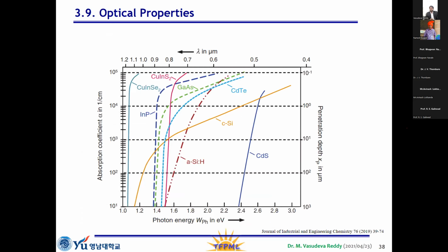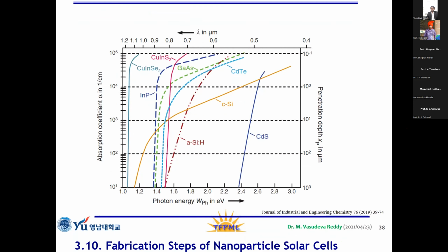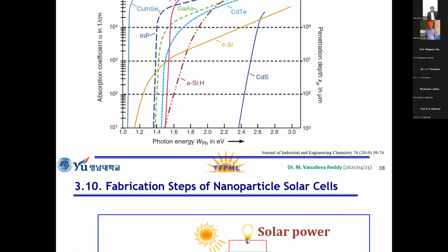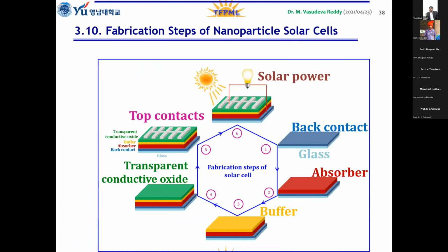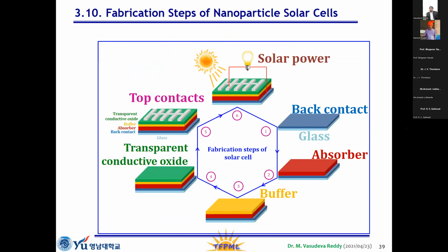which have the sharp absorption edge over 10^5. Similarly, tin monosulfide or antimony sulfoselenide, these two materials have a similar absorption coefficient. We can use almost 500 nanometer thickness of the material, that's sufficient to produce reasonably good efficiency, around 30% practically. So here I will provide the information on how to fabricate the solar cell.